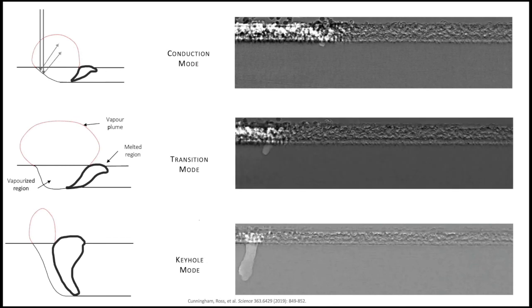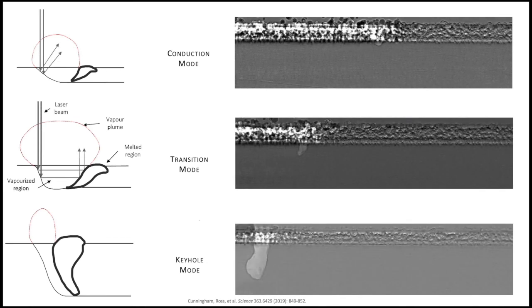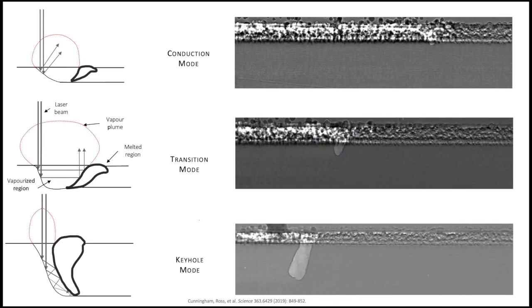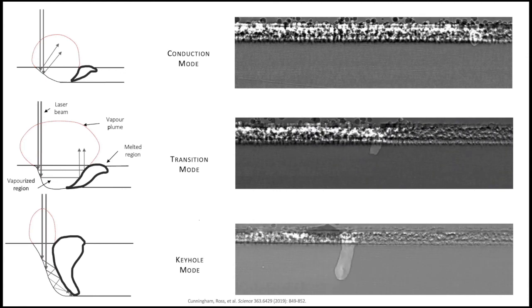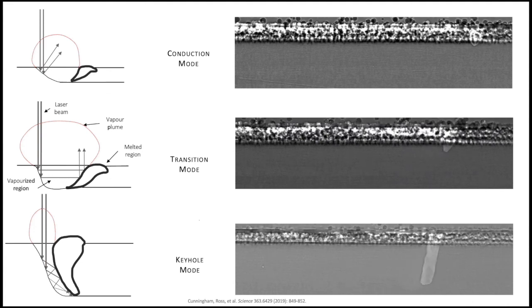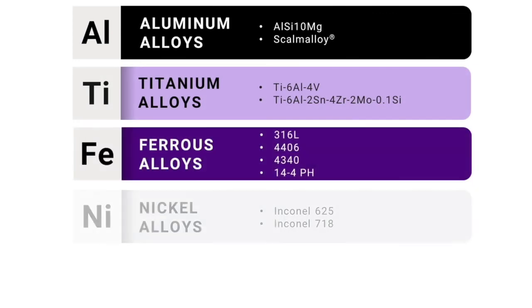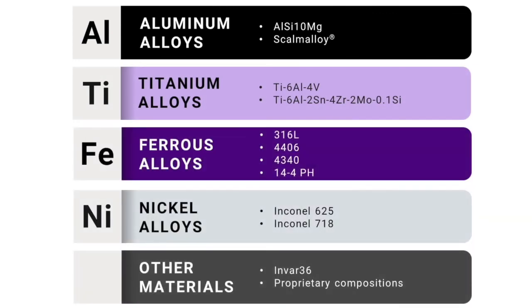Our goal was to develop process parameters for Scalmalloy in 2 weeks or less. The approach we chose was based on physics-based modeling theory. Our previous work in developing processing maps guided the prediction of the experimental boundaries of conduction, transition, and keyhole melting modes. This work has been validated with data sets from numerous aluminum, titanium, ferrous, and nickel alloys.